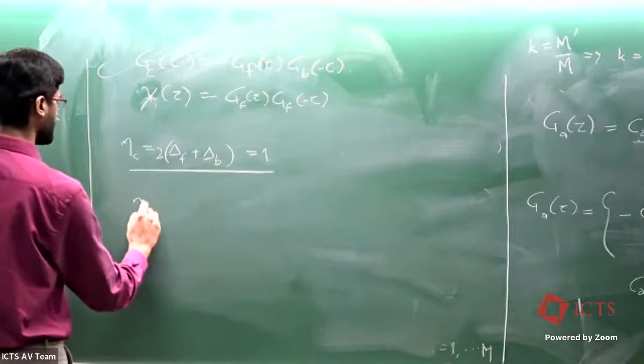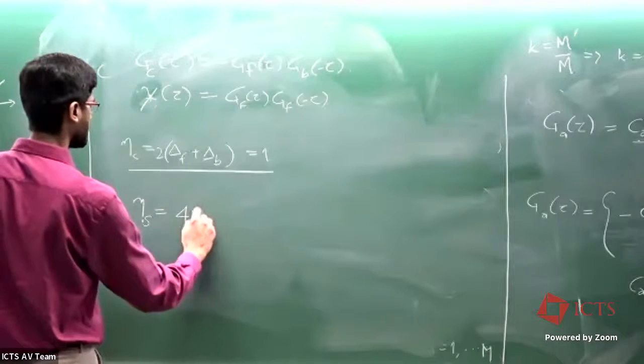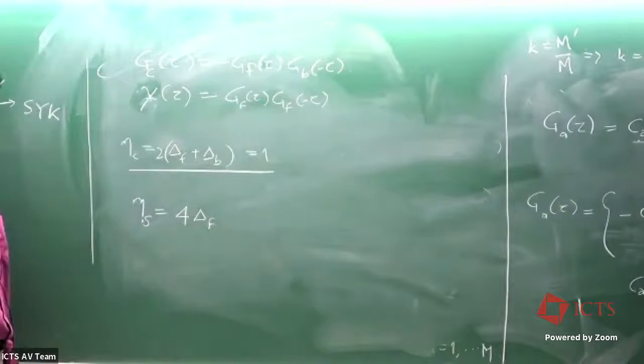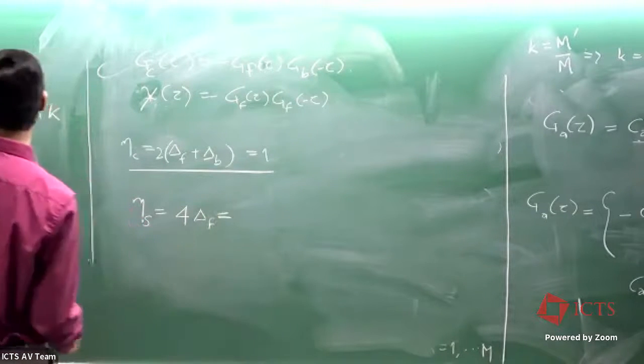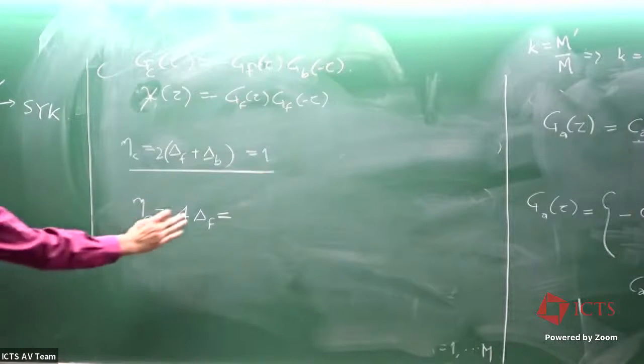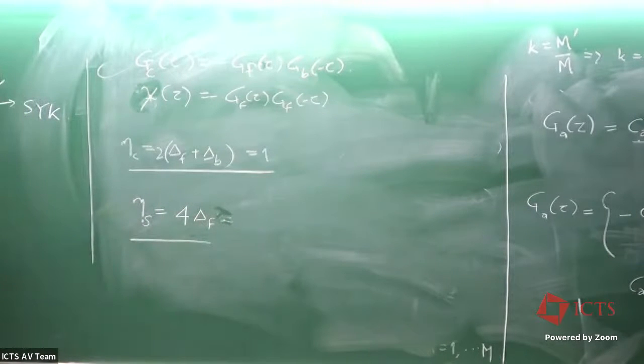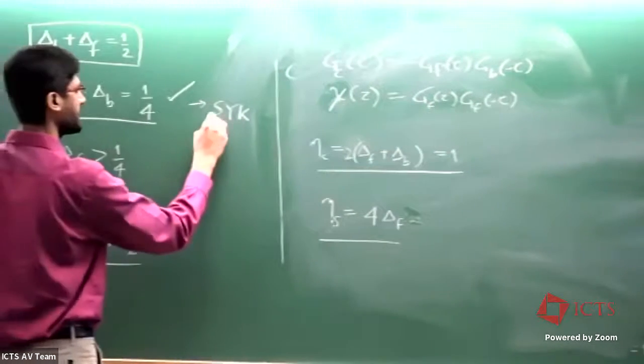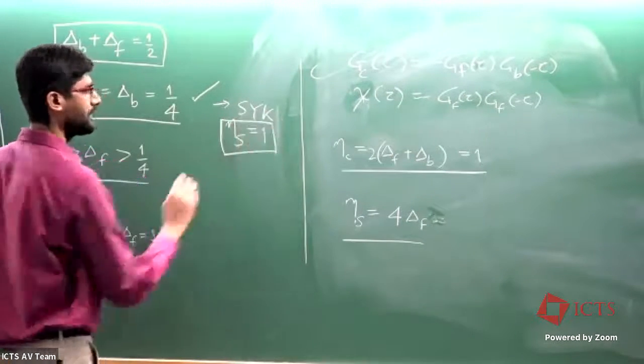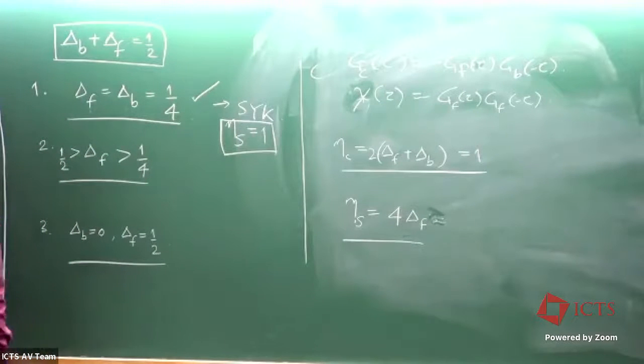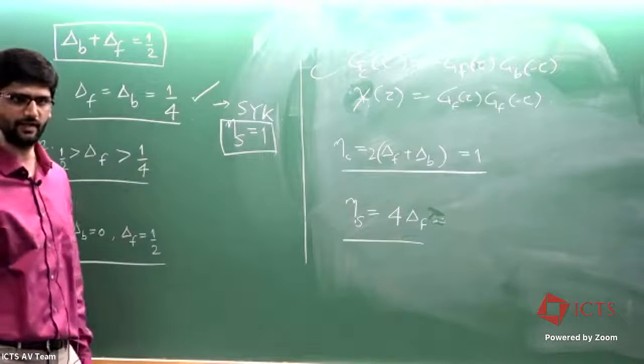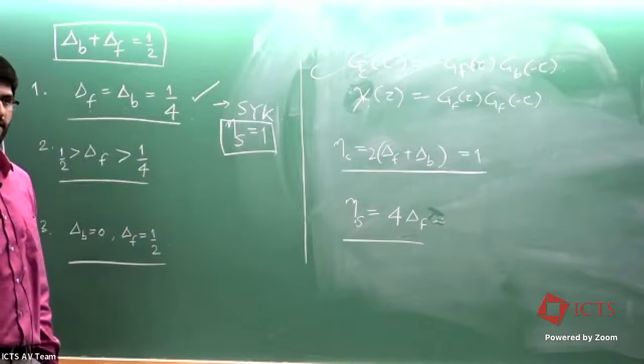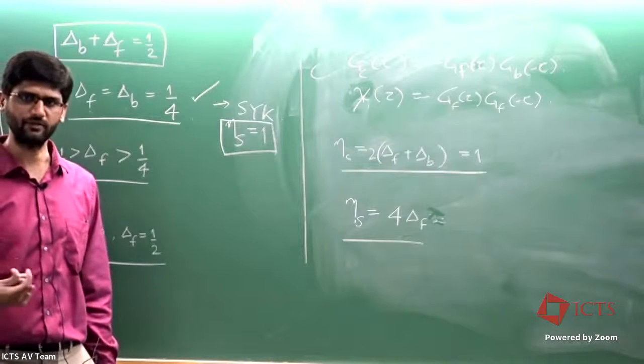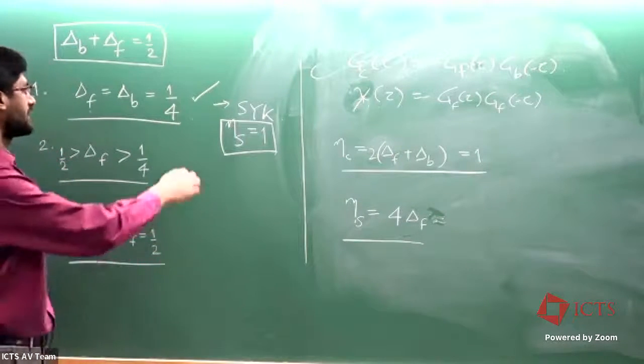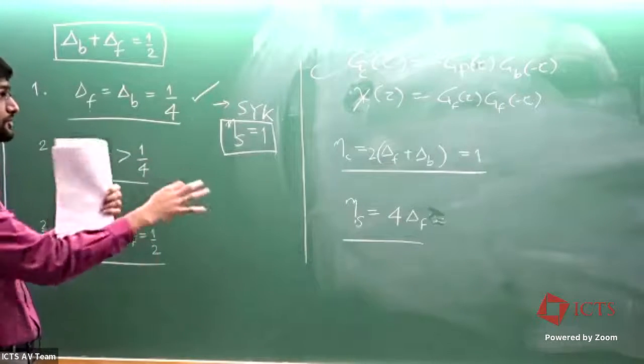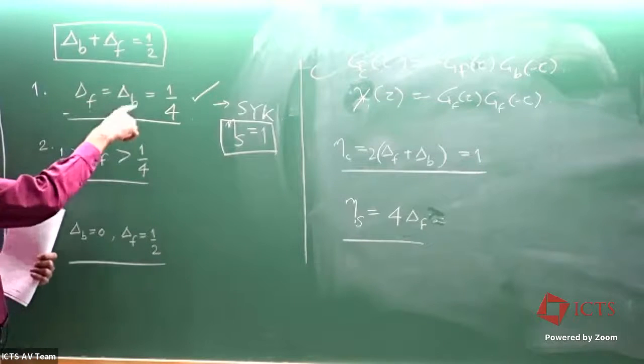Similarly, you can work out the exponent for the spin operator, and this is actually 4 times delta_F, simply because you have a product of 2 fermionic Green's functions. And this now depends on what type of solution you have. So let's look at these different solutions. For this, when delta_F and delta_B are 1/4, you get eta_S equals 1. So this was the marginal spin-spin correlator that we also talked about yesterday, and this is the type of SYK criticality, right? So the RG solution that I showed you yesterday, the non-trivial fixed point where eta_S and eta_C both were 1, in this large M parameter space, corresponds to this one where delta_F and delta_B are 1/4.